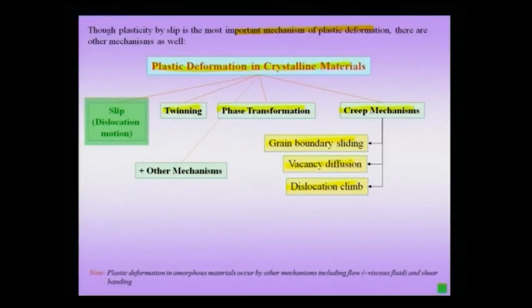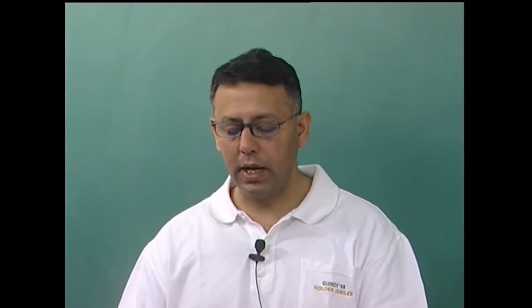We have to of course note that in amorphous materials, the plastic deformation mechanisms could be very different, and this could involve shear banding or even viscous flow, which is almost like a Newtonian flow, liquid flow, and this typically, for instance in bulk metallic glasses, takes place above the glass transition temperature of the bulk metallic glass.